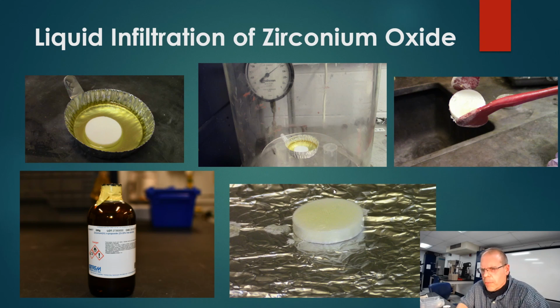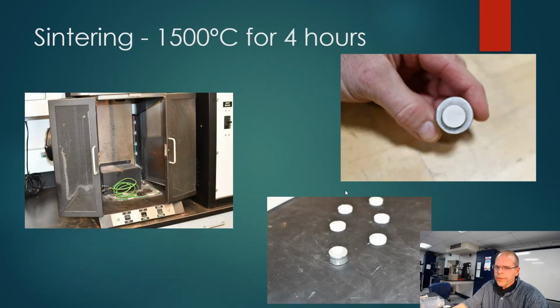Again, the thing that's kind of tricky about this, if you do this and you wait 24 hours for your puck to dry and you weigh the thing, you might say, oh, Don, I don't have enough zirconium oxide. You have to repeat the process. Now, if you have too much, unfortunately, what that means is you either have to restart with another disc, or you could stick it in the furnace a little bit, see if you can heat off some more of that alcohol and come up with a better mix. But again, the goal is simply to have zirconium oxide absorbed in your aluminum oxide.